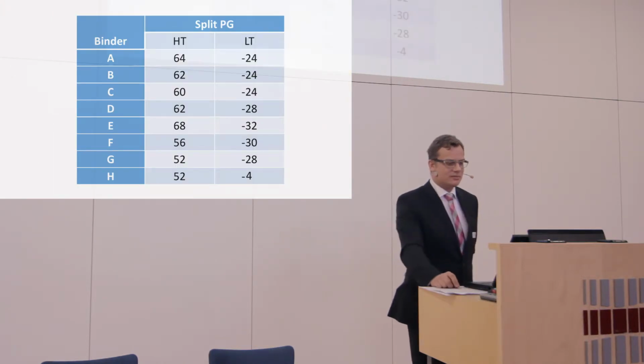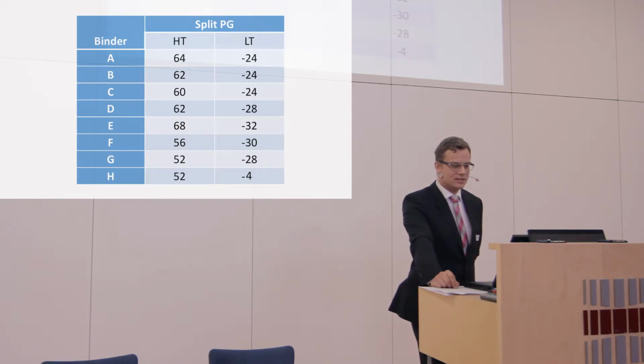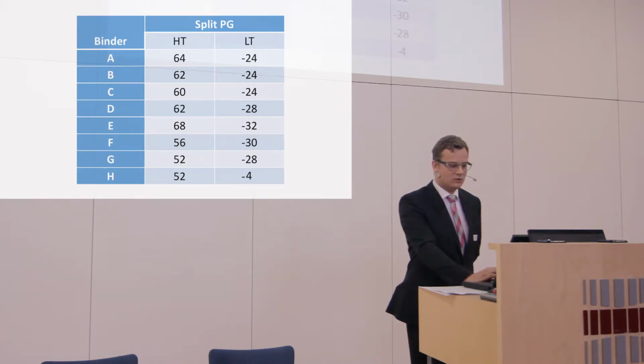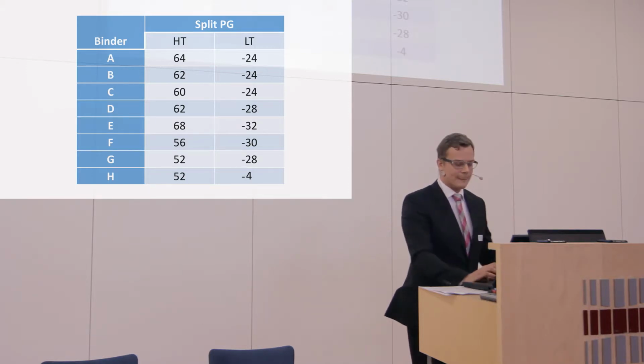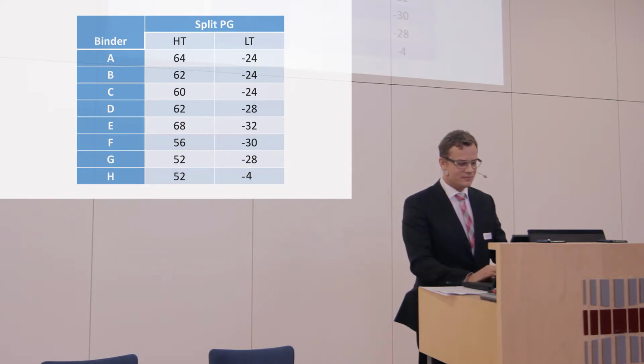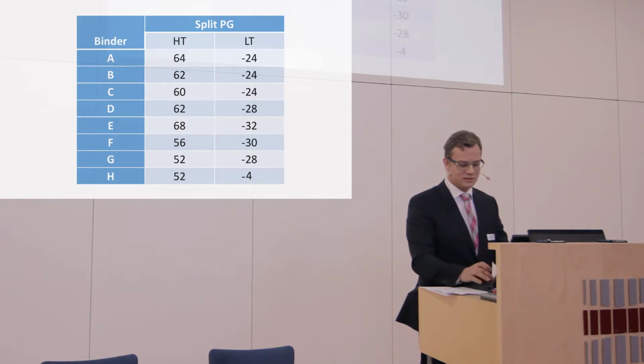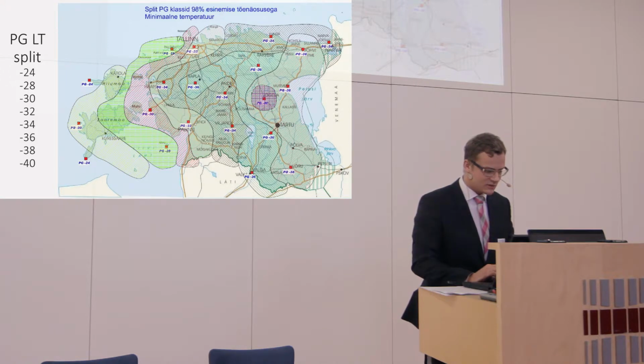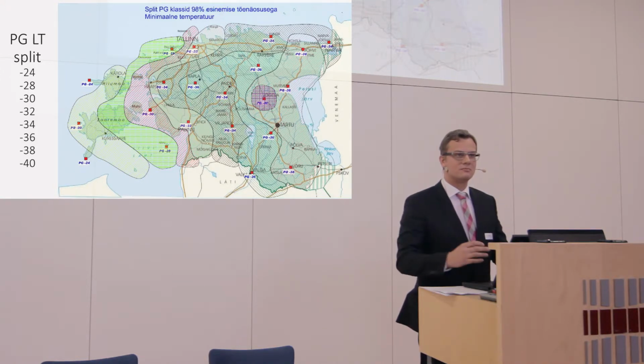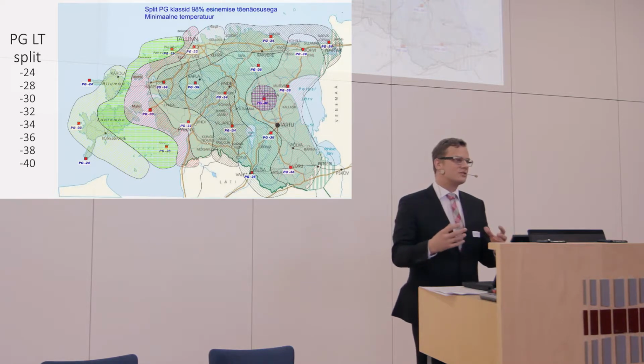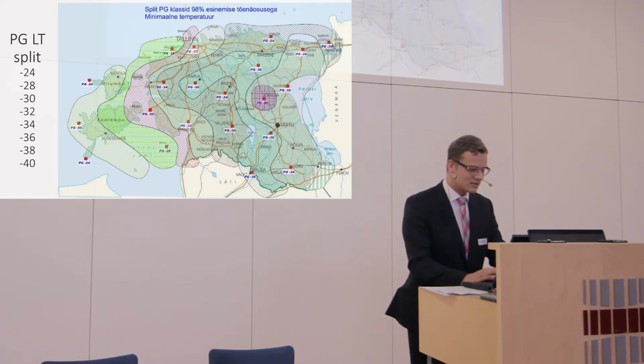Then we looked at the bitumen according to split grade. As you can see, these are neat unmodified binders. We have covered almost all bitumen for the high temperature, but none of the bitumen could meet low temperature. So we have quite a lot to go from this low temperature to the point where we need it to be. For example, for binder A, you have 64 degrees and -24 degrees, and you can see -24 only here. So this bitumen, in the sense of low temperature, you can use it only in this region, not anywhere else.